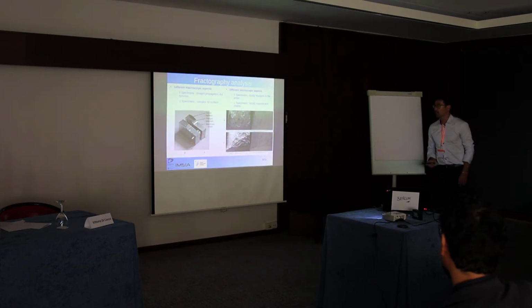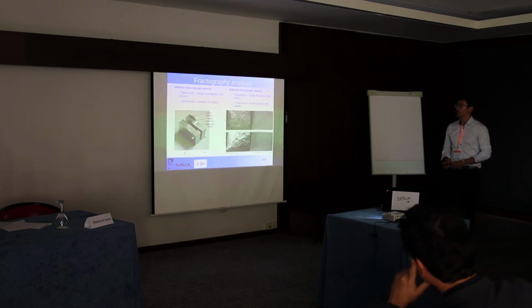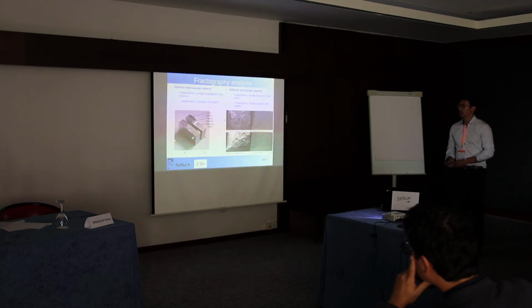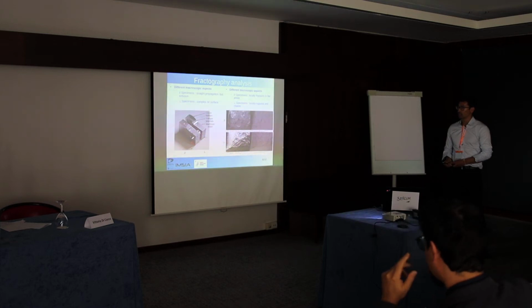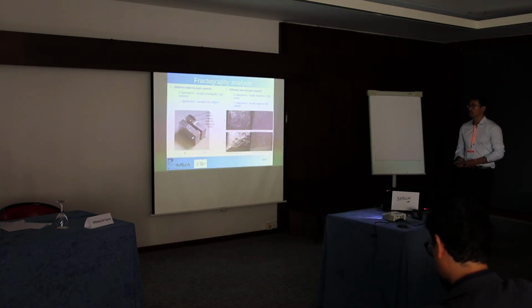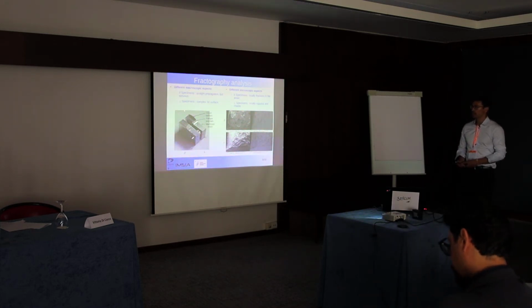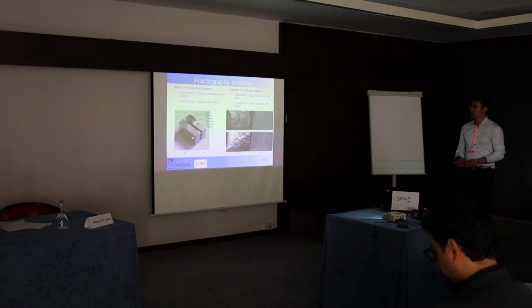So here you can see the fracture surfaces. On the left-hand side is the macroscopic aspect. For the parallel specimens, we see that the crack propagated in a straight fashion in the symmetry plane of the sample. However, it is quite tortuous. For the second specimen, there are some complex 3D phenomena occurring, with this region here being a little bit elevated and this region here a little bit shallow.